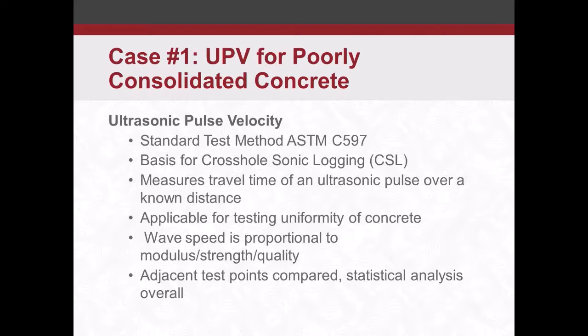But one of the things that we do is we analyze adjacent test points. So if we see a big variation in wave velocity over a short distance, say 1 or 2 feet, then we know there's some sort of non-uniformity there across that distance of 1 to 2 feet or whatever that point spacing is. The other thing we do is some statistical analysis on the data, see what the highest wave velocity is, lowest wave velocity, the averages. We do some standard deviations to see what our range of wave velocities are.